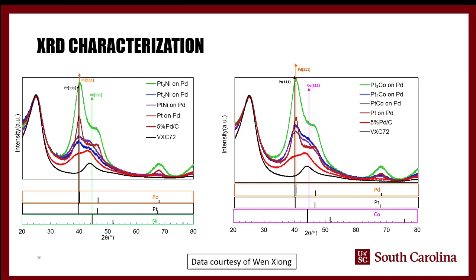So here we have some XRD characterization. We have to be a little bit careful with the XRD characterization because the particles are pretty small. But the way we get around that is to basically deposit a large amount of the metals. And so you end up with large enough particles that you can do XRD characterization and be confident in the result. And so what we see here is when it's just the 5% palladium, we've got just the characteristic palladium peaks here and here. They're not very crystalline, so they're not really well defined.